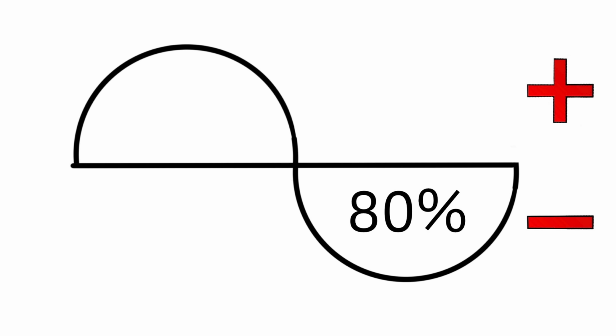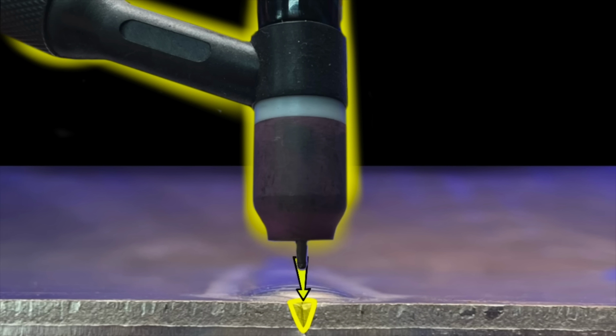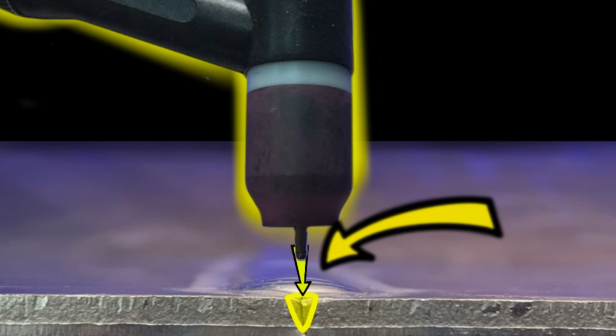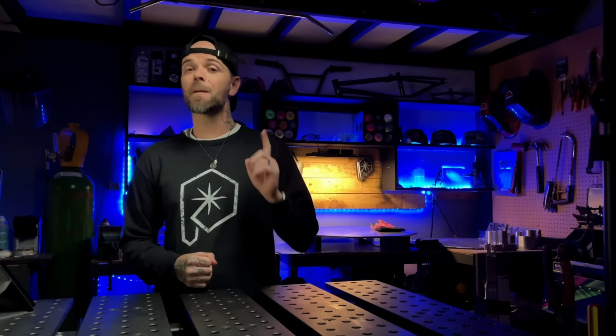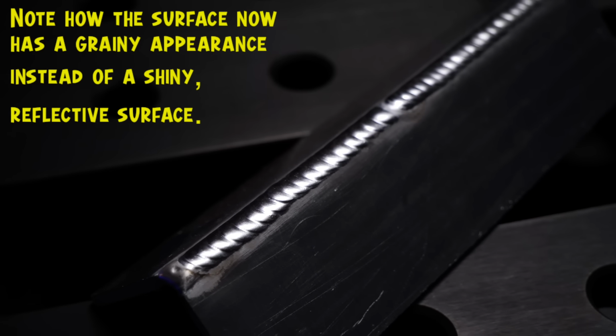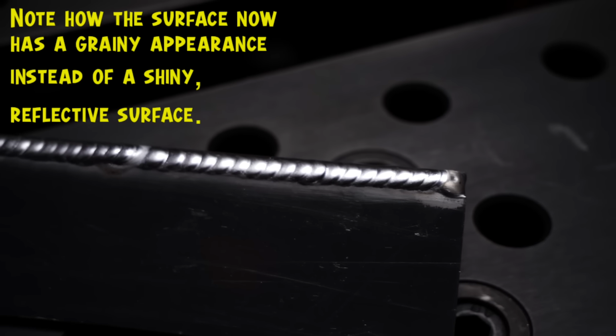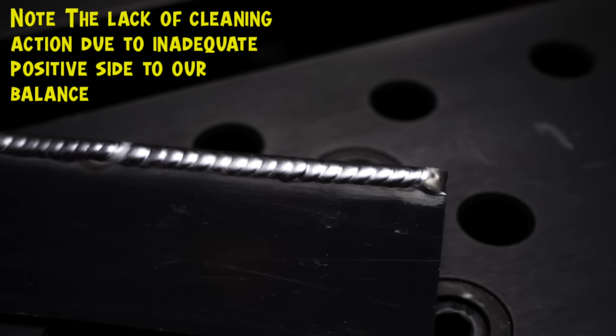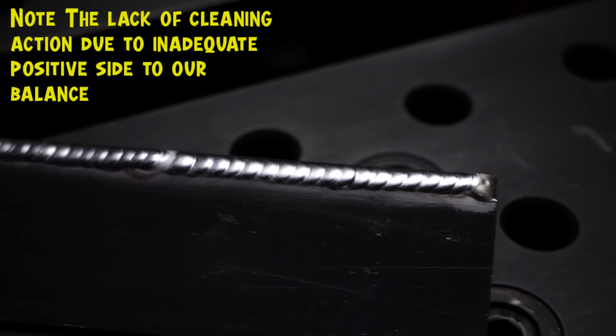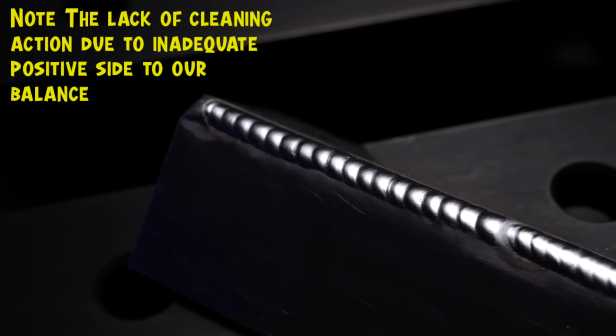Like I said, a general ballpark for balance is probably going to be somewhere around 80% negative. This is going to allow for good penetration and thoroughly directing our heat input into the base material. Now, the more you turn up your negative side, obviously the more you're going to get this effect into the base material. However, there will be a point of diminishing returns here. As we begin to run an insufficient amount of our positive side, what we're going to start to see is our weld is now going to start to look dull. It's going to lose the shiny reflective surface we want. So now essentially we are not getting enough of our positive side that we need. And when this happens, it's not going to provide as much cleaning action. It's not going to clear oxide off the weld. We're not going to get as clean results.